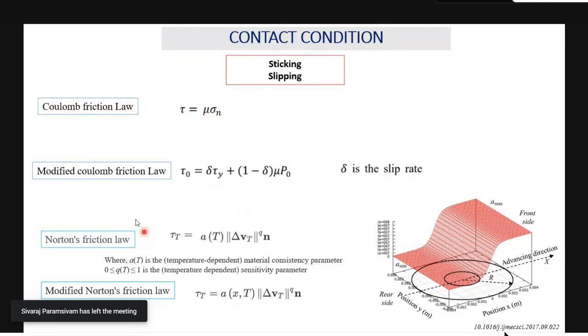Another model is the Norton friction law. In this model, the critical shear stress, the contact stress, is based on the sliding velocity. This sliding velocity is further influenced by parameters A and Q. A is the material consistency parameter, which is based upon the flow strength, and then we have the sensitivity parameter, which is very similar to strain rate and other factors.